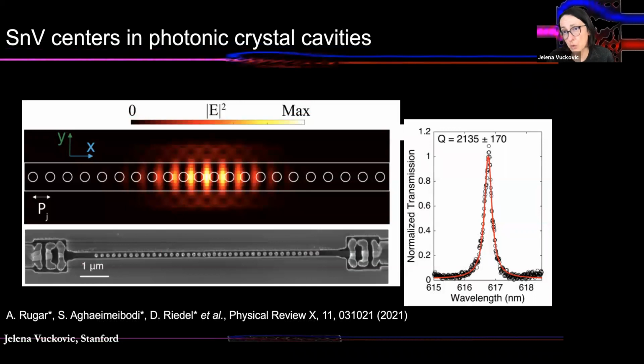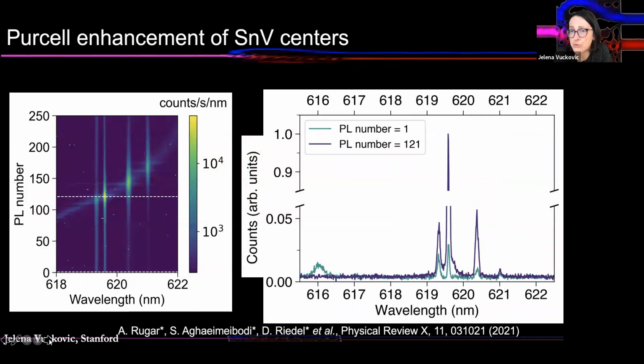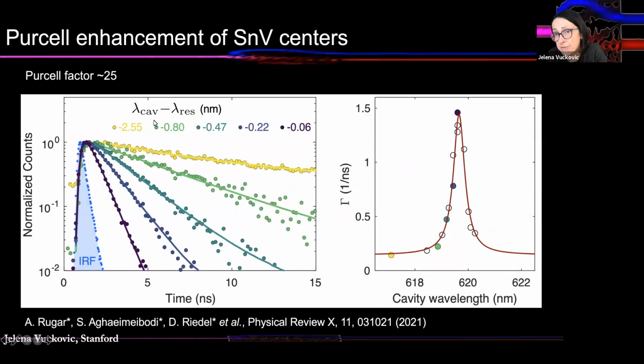So recently, we've also shown that you can implement these photonic structures and also have tin vacancies inside of the structures and not degrade their properties and have an excellent photonic interface. So that's an example shown here, a diamond cavity with high Q factor, tin vacancies inside. And of course, that's very important because when you make photonics for quantum applications, you don't want to affect the properties of your color centers. And then when you tune your cavity across transitions of your tin vacancies, you see them light up because you have large Purcell enhancement. And as of now, we have a Purcell factor of around 25, strong spontaneous emission rate enhancement. And we redirect most of the emission into a single mode that we can collect, which is very important.